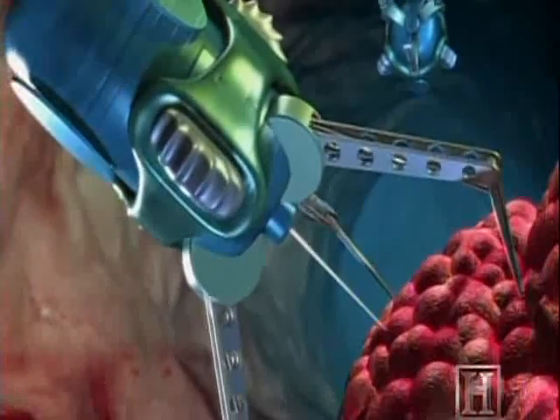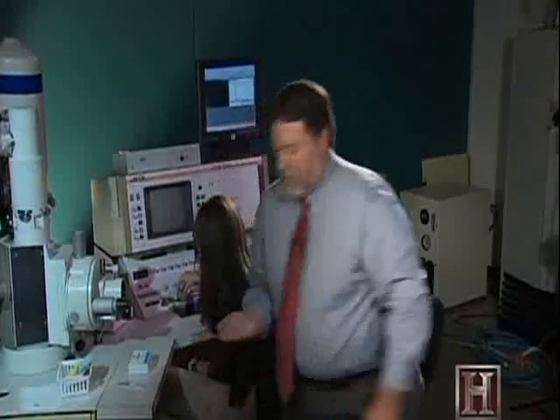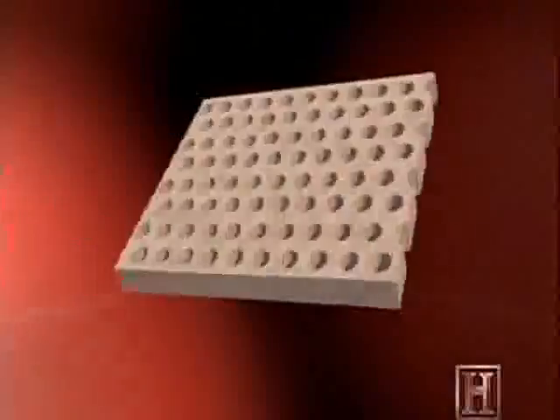Such intriguing technology can only be contemplated because of recent advancements pioneered by researchers like Dr. Teeters. He discovered that small porous aluminum discs, originally developed as a filtering medium, provided a superstructure to make more than 1 billion nanobatteries at a time. One of the first steps in the manufacture of these nanobatteries is to check the integrity of the alumina films that have the 200 nanometer diameter pores.